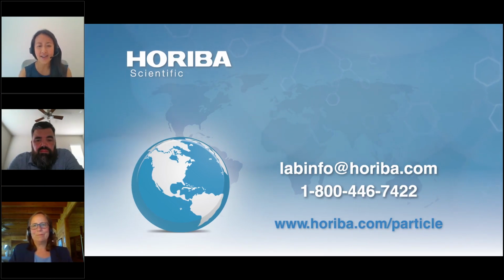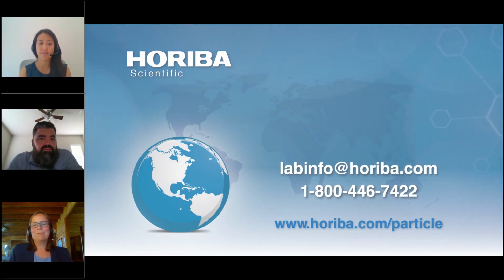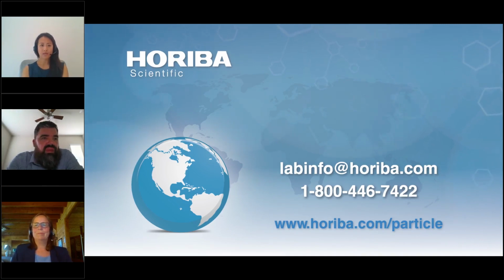I work with nanoparticles called cubosomes. They can present very squared shapes. So the measurement for the hydrodynamic size would be a sphere that represents the motion of my square particles? In a lot of these light scattering techniques, you make the assumption before you ever go into the lab that everything is going to be spherical. It doesn't mean you couldn't extract some more information, but with the symmetry of a cube, not something I have experience with, I doubt you'd see much difference from a truly spherical sample.